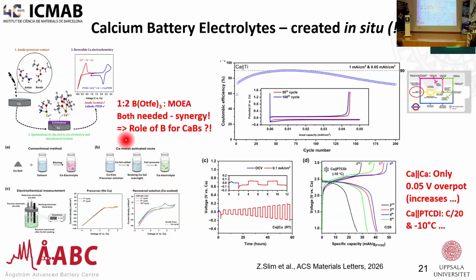But the thing is that we need to balance very much what we're using as a system. So we have a borate system here, and the thing is, if we don't have both these components, we actually don't get it at all. We don't get it to cycle. And then a big thing that also Alexandra has been taking on here is that there is a certain role of the element boron for calcium batteries. It seems to be extremely instrumental that you have that present in the interface between electrode and electrolyte. Otherwise, you don't get it. So we can cycle cells. We can cycle cells with a rather low over potential. We can do it at rather low temperatures, like -10 degrees.